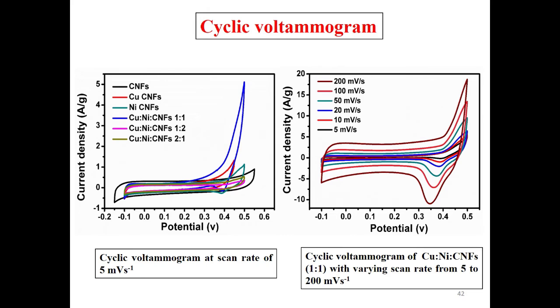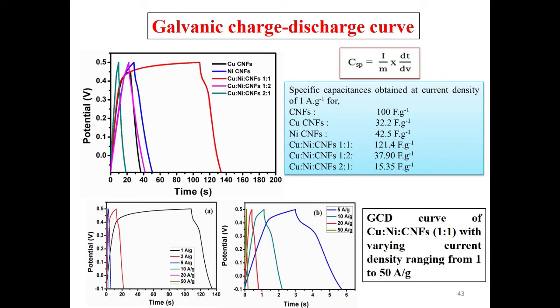When we talk about the cyclic voltammogram of copper nickel carbon nanofiber with varying scan rate from 5 to 200 millivolts per second, at 20 millivolts per second the material shows a very stable response towards that particular potential. Galvanostatic charge discharge curve: here copper nickel carbon nanofiber of 1:1 shows very high charge and discharge compared to the other ratios, 1:2 and 2:1, and to nickel carbon nanofiber. The GCD curves with varying current density from 1 to 50 ampere per gram show very high efficiency.